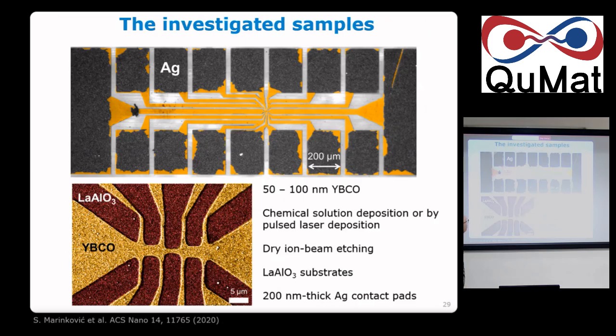So these are our samples. YBCO is the yellow stuff. The gray you see there is silver, because you want an ohmic contact so you don't shoot heat in there. If you look at the center, it looks like this. And this is where it comes to your question about directionality. I make a small bridge in the center, but then I make two other bridges on the side, so I can see where the oxygens are going. Because I don't measure only this, I also measure what happened here and what happened there.